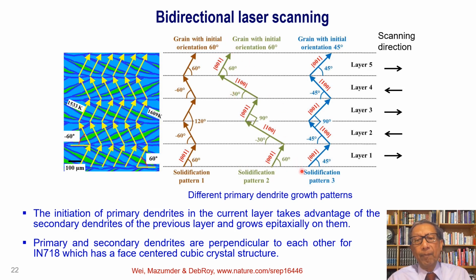The data are consistent with solidification pattern 3 shown here, where the primary dendrites grew from the secondary dendrites of the previous layers. The secondary dendrite of this layer is perpendicular to that layer, and that's where the primary dendrites of the next layer grow. And the growth pattern is zigzag in adjacent layers. It shows how the growth patterns can be adjusted by changing the scanning pattern.